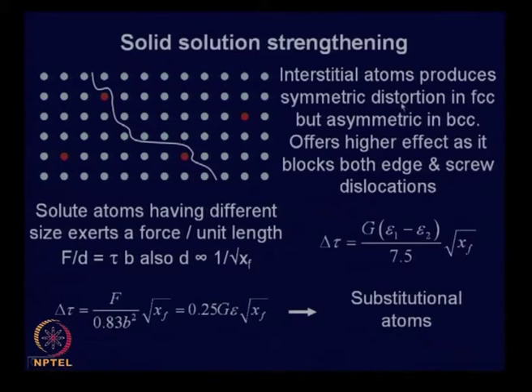and therefore, interstitial atoms produce, as I summarized here, symmetric distortion in FCC, but asymmetric in BCC, and asymmetric distortions are more effective in blocking dislocation movement, because uniform stress can block only edge dislocation movement, whereas asymmetric distortion will have shear stress, and therefore, it can block the screw dislocation motion as well. So, therefore, they are a much more effective barrier to dislocation motion, and they have a high amount of strengthening effect, and this also will nevertheless be proportional to the number of atoms that you have. It is also proportional to square root of atom fraction. So, this is applicable for interstitial, and this is the relationship for substitutional atom.